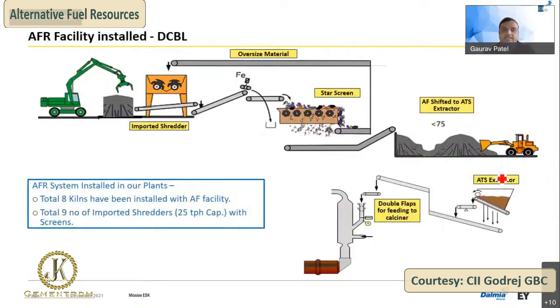This is the facility installed in DCBL, with imported shredders and then the magnetic separator to avoid damage to the refractories in the calciner at the feeding locations. Then there are the star screens. Whatever material is there, we shift to the ATS extractor and then double flaps and feed to the calciner. In total, 8 kilns have been installed with AF facilities, and a total of 9 imported shredders of 25 tons per hour capacity with screens have been installed in our DCBL.